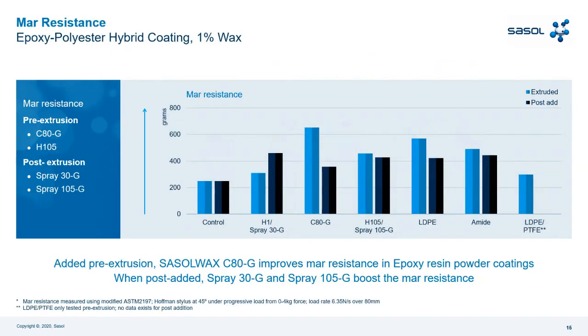Then mar resistance, always in epoxy resin, of course. We have again pre-extrusion and post-extrusion. In pre-extrusion we have Sasol Wax C80G, again the micronized version of the Fischer-Tropsch wax with melting 80. The control has a very low value, so you need to check in this result the highest value. The highest value in pre-extrusion you have with C80G, Fischer-Tropsch, then in epoxy, and then follows H105, that is a coarse powder with a melting of 105.